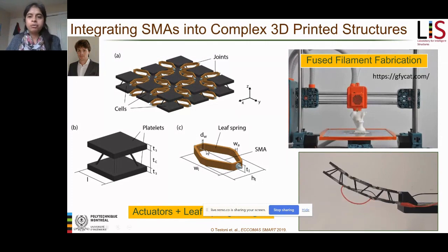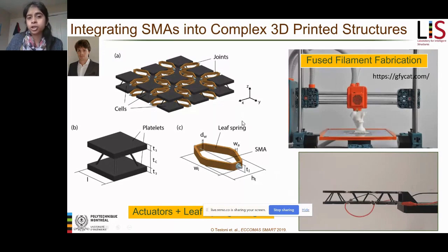But the problem was he was trying to print and do things. He wanted a material that was cheap and lightweight, and so he 3D printed these truss structures with PLA. Because the SMA transition temperature was about 120 degrees, higher than the Tg of the PLA, we had to use leaf springs made from a material with a really high Tg. So we went for PEEK, and he printed PEEK leaf springs on a different printer, and then he sat down to assemble this whole structure.